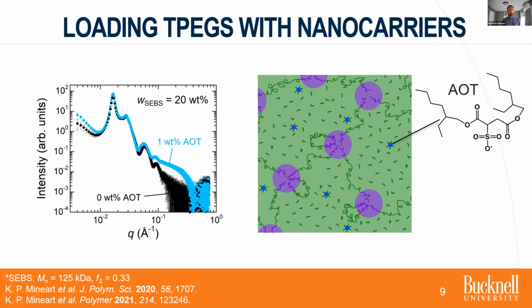For proof of that, we did small angle X-ray scattering, so I'm showing you a couple of curves here on the left, which I'll get a lot more into on the next slide. But the general takeaway here is we can formulate gels that have the same amount of copolymer, in this case 20% of our triblock copolymer, which I should point out is about 1/3 polystyrene end blocks, and is 125,000 grams per mole total, Mn, number average molecular weight.